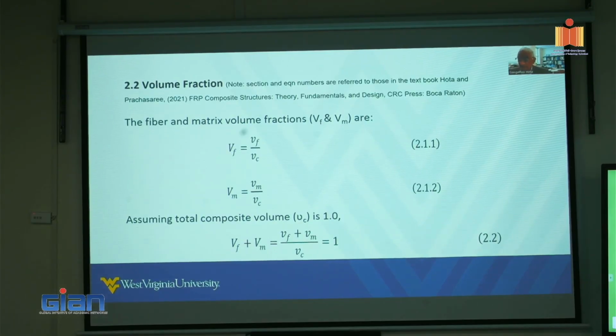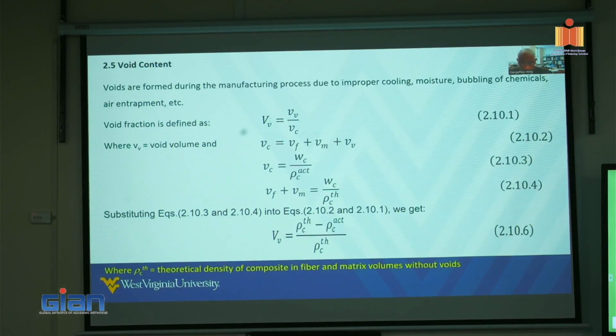The next slide talks about voids and how they are formed during the manufacturing process due to improper cooling or excess moisture, bubbling of a chemical, or even overcrowding of fibers. Similarly, resin-rich areas are possible, which lead to strength degradation. However, we are going to be assuming, as you see in my next slide, that these fibers are uniformly distributed, and also the resin is uniformly coated around the fibers.